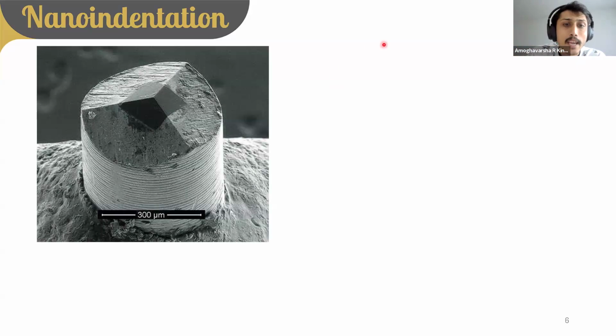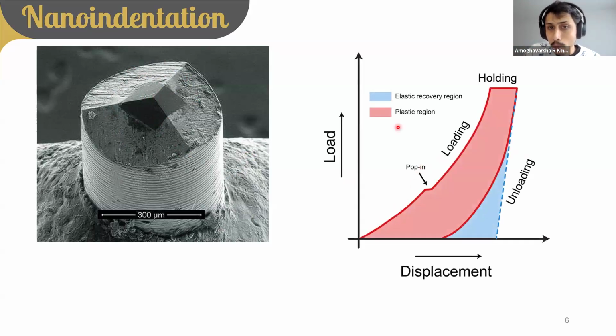For that, we use a diamond tip, and the shape of tip can be different, like a spherical tip, conical tip, or any other tip. But this kind of tip is called a Berkovich tip, which is very efficient to study the mechanical properties of molecular crystals, that is crystals of nanoclusters. Here we use a 400 nanometer diameter diamond tip, which is indented into the sample and taken out of the sample. And during this process, a transducer will read the changes in the load and displacement of the sample. That is shown here in the graph as load displacement curve.